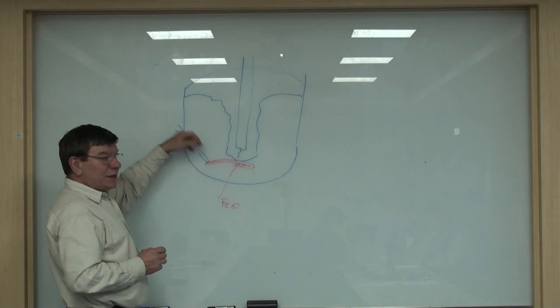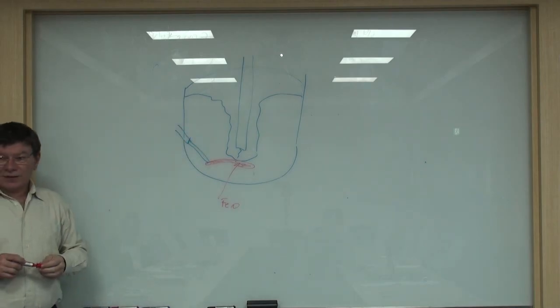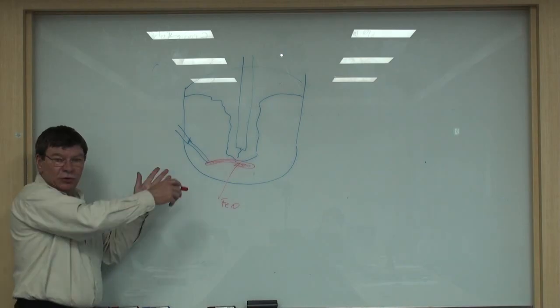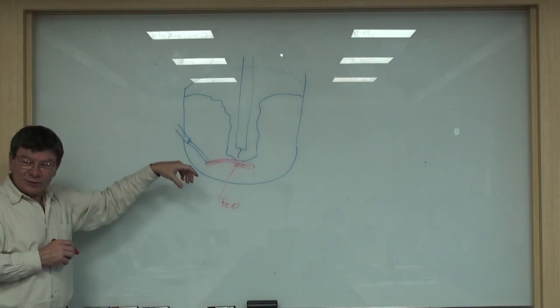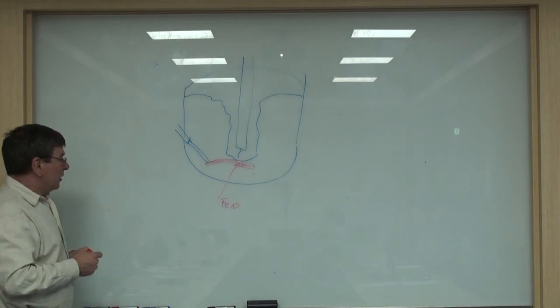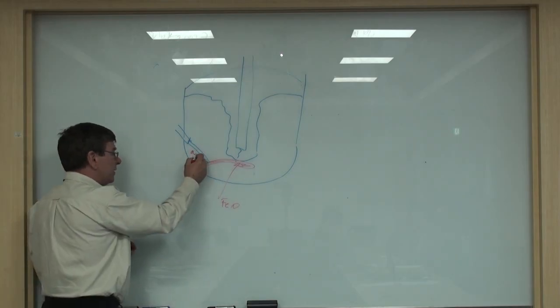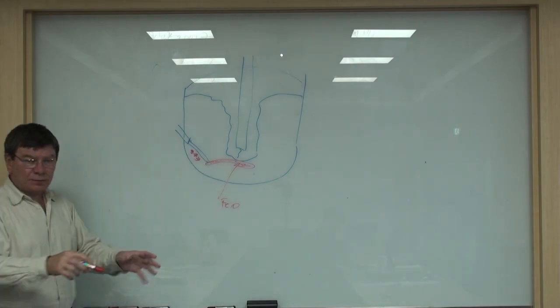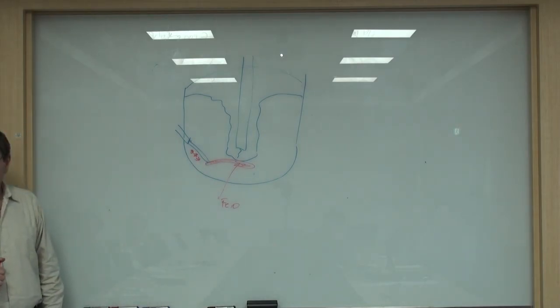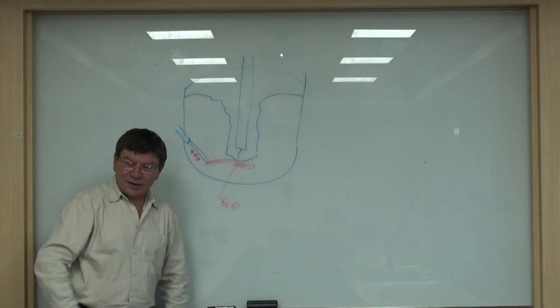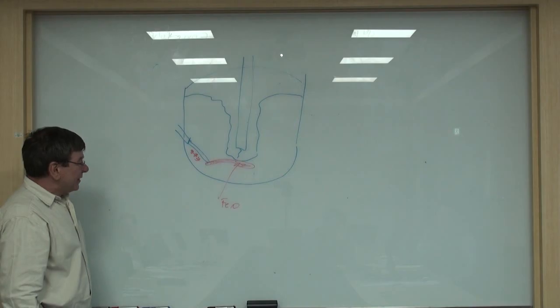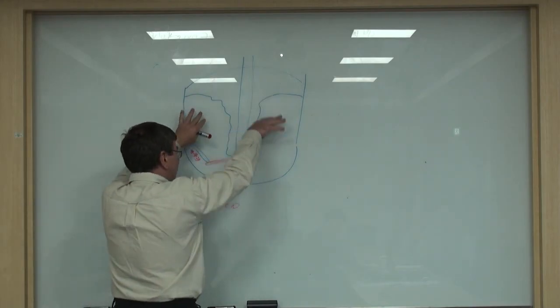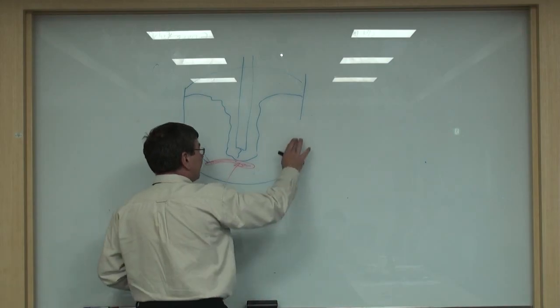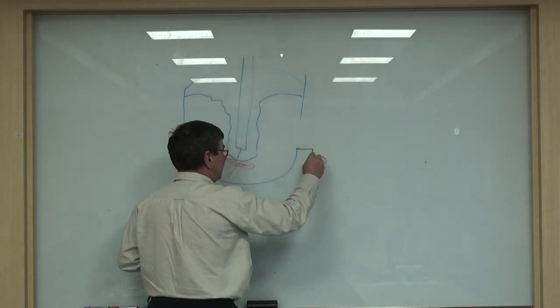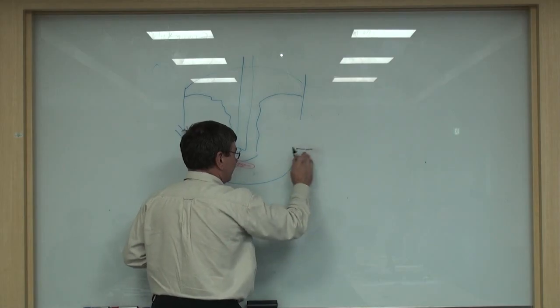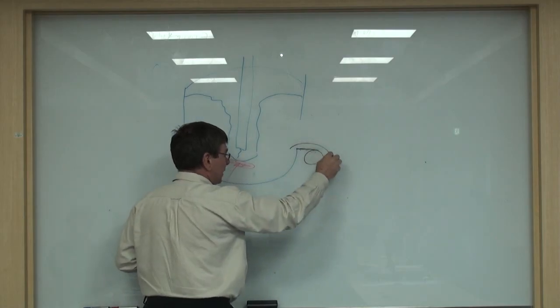And there is no access to inject carbon, even if furnace suppliers say, okay, this is a module, on top you have the burner, and below you have the carbon injection. But in most cases, carbon remains here because there is no room and there is no liquid to react. And the FeO is escaping. So what happens when the scrap goes down and the first slag goes out of the furnace.